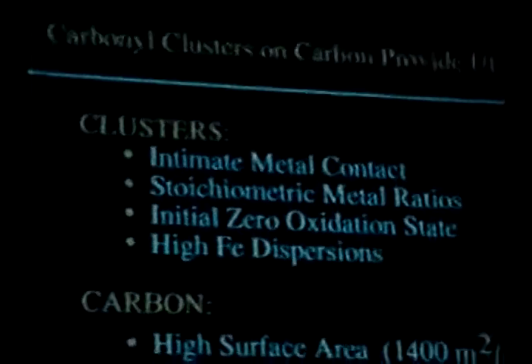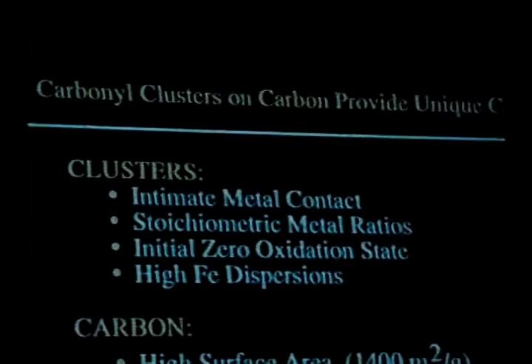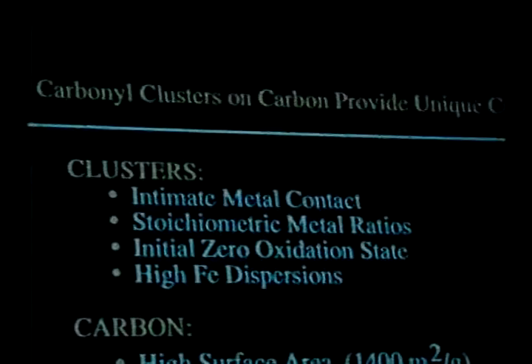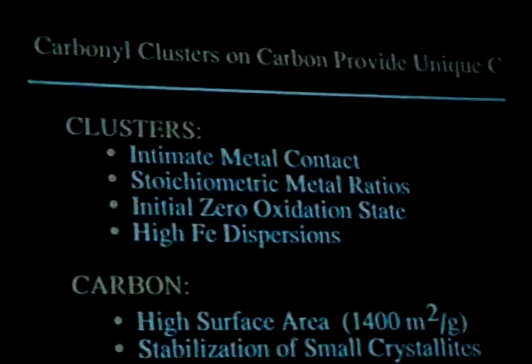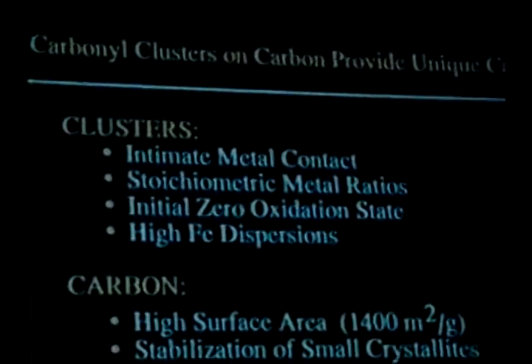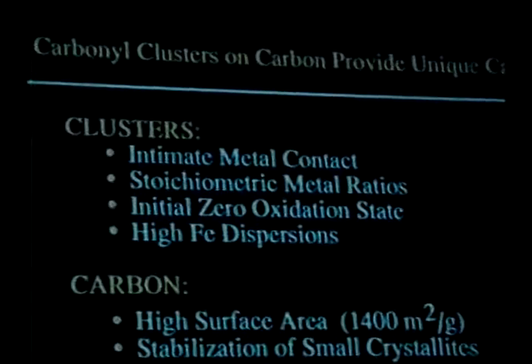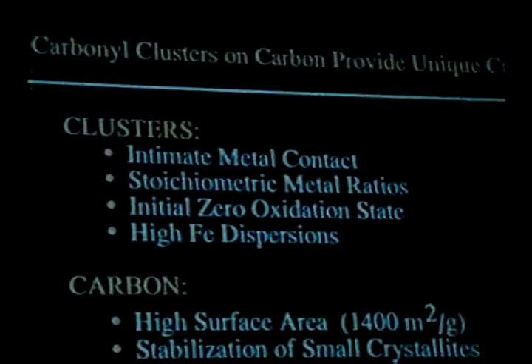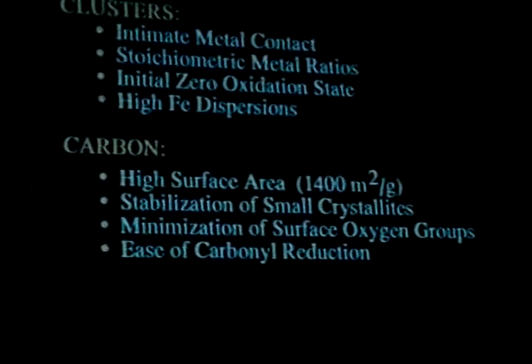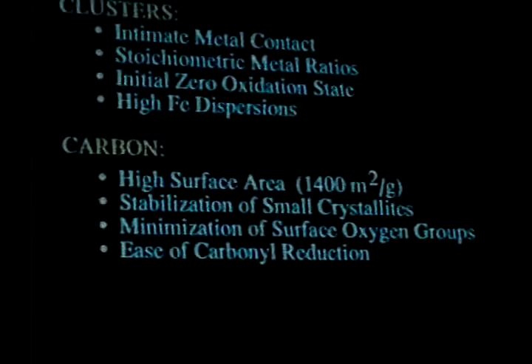We used the organometallic carbonyl clusters as precursors for our iron manganese catalysts. We noticed that these clusters have a few very interesting properties that we want to exploit. First of all, they have an intimate metal contact prior to impregnation onto the supports. Secondly, we get a stoichiometric metal ratio, so we can prepare these catalysts to exactly the ratio that we want of iron to manganese.